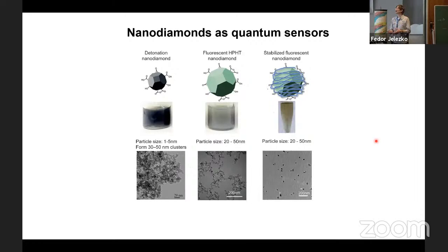And actually, after functionalization, the diamonds get more stable because this coating can be charged, and you want to avoid aggregation. Often, just after crushing, diamonds are very much aggregated together because of residual carbon sp2 type groups on the surface, and hydrophobicity. After this functionalization, or even coating with charged polymers, diamonds are much more dispersed. They don't aggregate. They can actually be transported in cells.